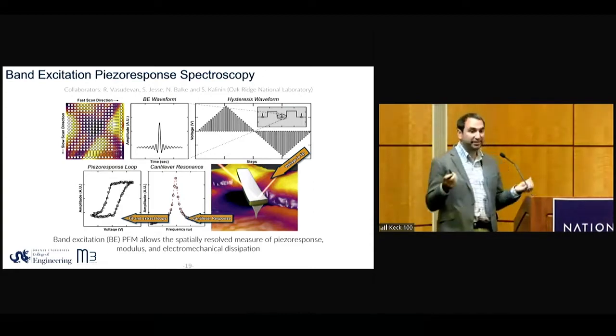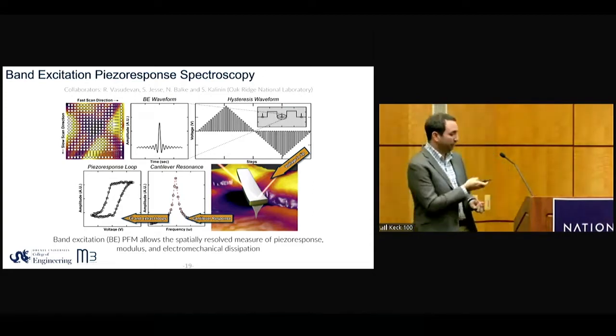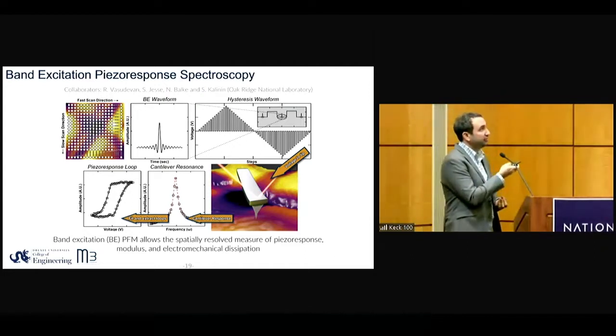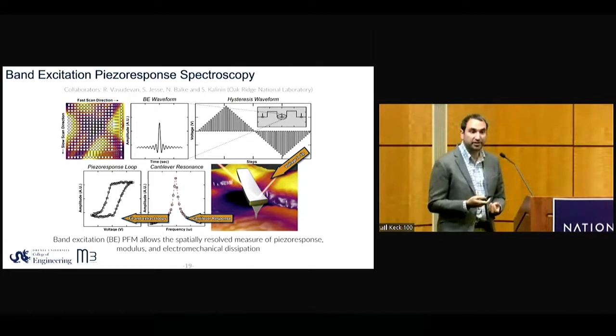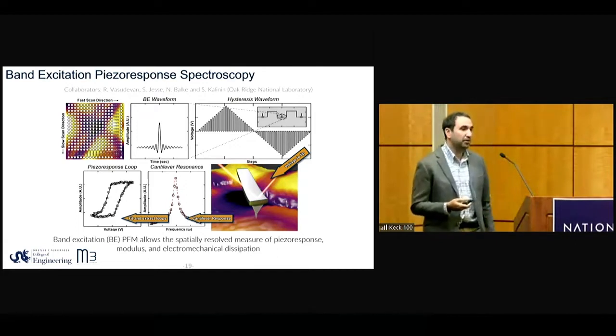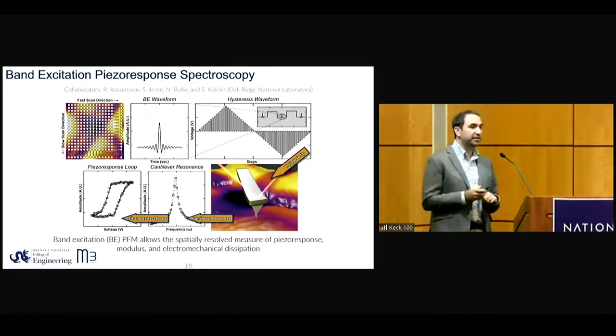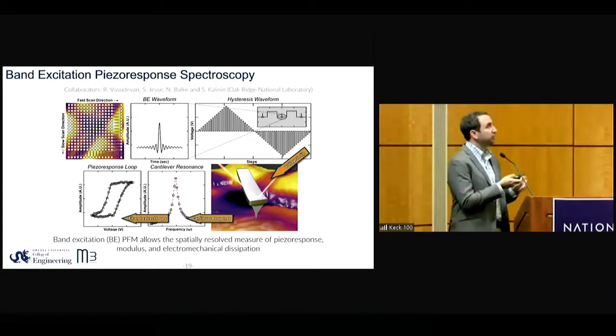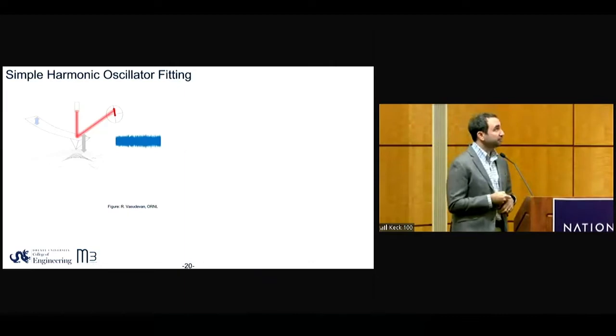So this is a multi-frequency measurement, and what you want to do in this data set is fit these individual cantilever resonances to a simple harmonic oscillator model. And those are coming out at about 4 milliseconds per individual resonance response. And if you wanted to do this in real time, could we do this?